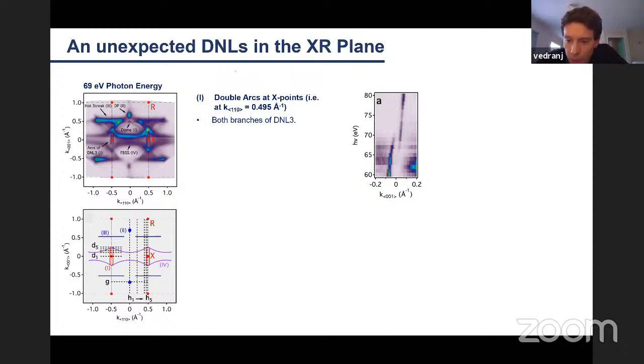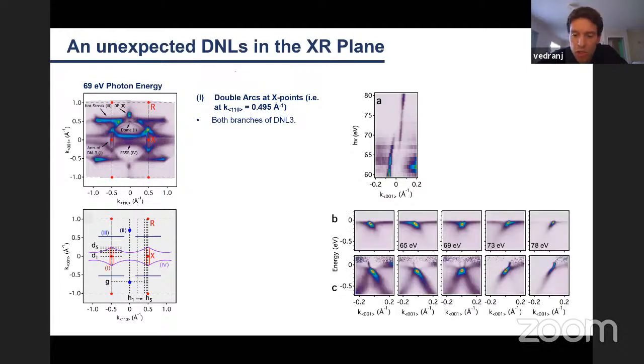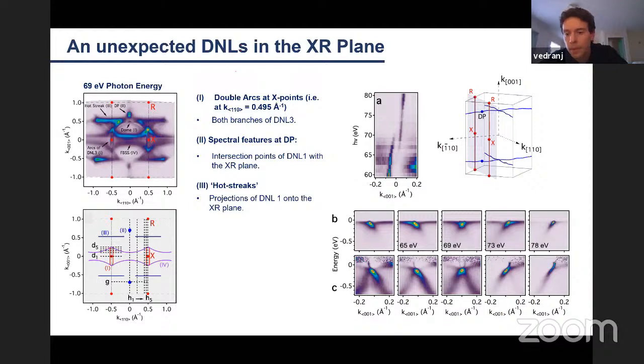And so second, we find these intense spectral features labeled DP in the top left. These are the intersection points of DNL1 with the XR momentum plane. And third, we find these hot streaks that you can see in the top left, and I've labeled them here. Their intersection with the XR line, with the Brillouin zone boundary, marks these hotspot features in the Fermi surface, and they are actually claimed to be responsible for the magnetic instability in ruthenium dioxide.